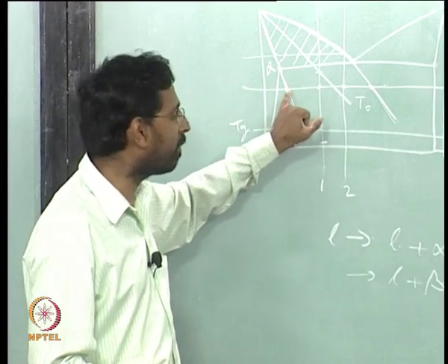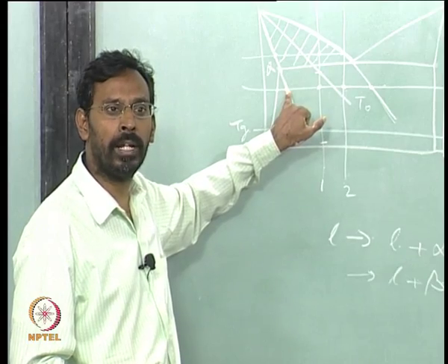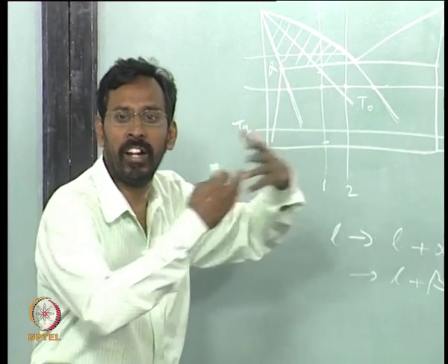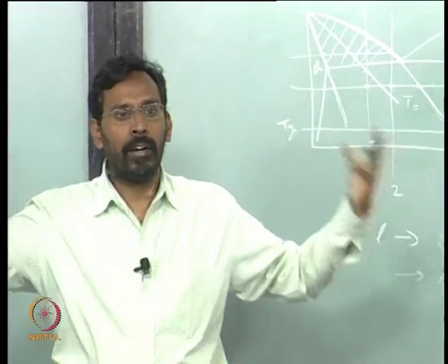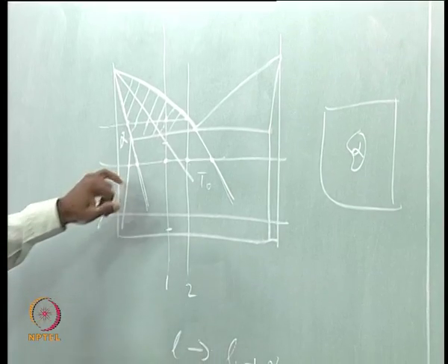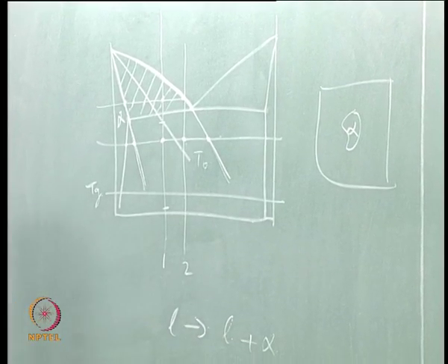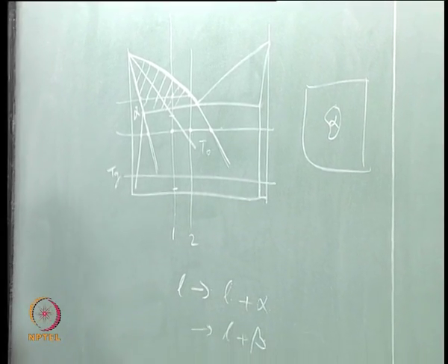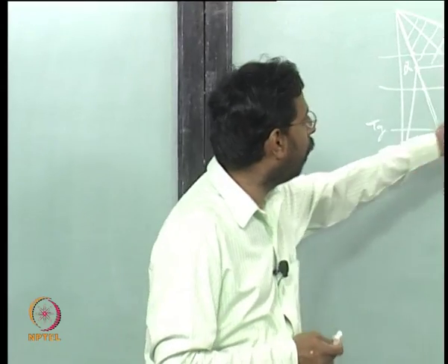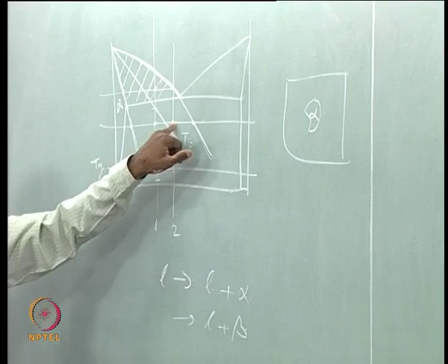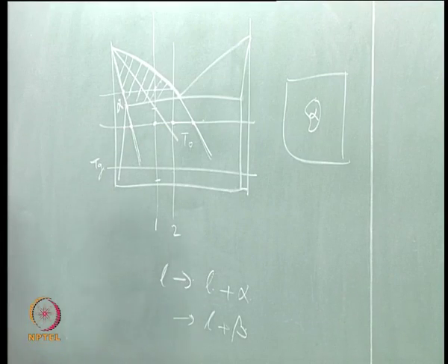So, the excess B atoms which are available in alpha will be rejected out of alpha and will go and join the beta, so that the beta quantity will increase, and then the alpha composition will get shifted towards richer A, and that is how the whole process happens. This is all assuming that partitionless solidification is not taking place.